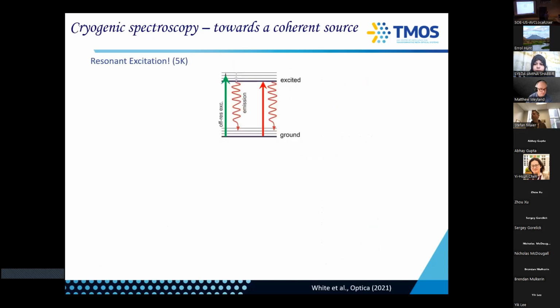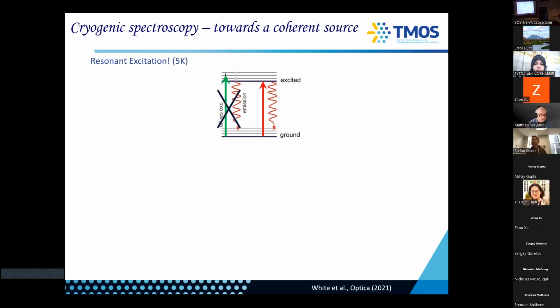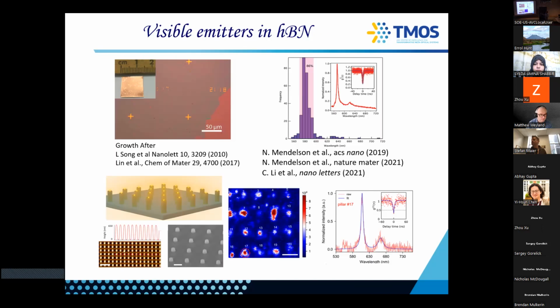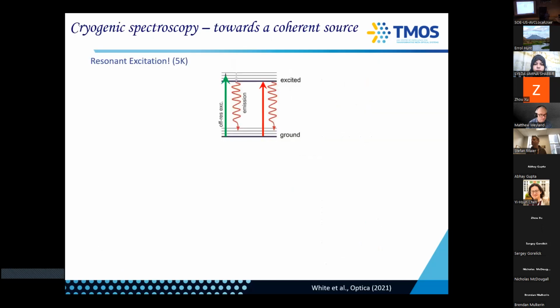For that, we really need to go to resonant excitation. Typically we excite with a green laser, as I mentioned, at some 2.4, 2.5 eV, to get the defect. For resonant excitation, we excite exactly at the same wavelength. So for our emitter that emits at about 600 nanometers, we bring in a tunable laser, park it right at the resonance of the emitter, and trigger it. The collection is quite challenging because you can then only collect the phonon sideband.